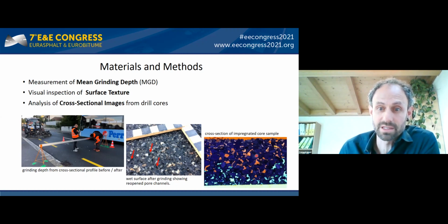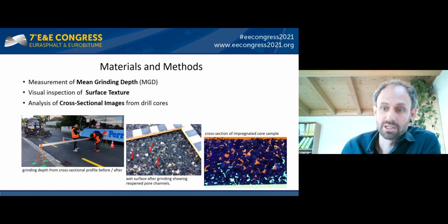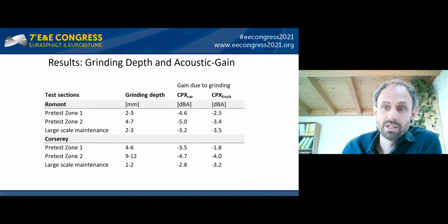Further analysis we used was cross-sectional images from impregnated core samples. With this special method, the top layer from the core was impregnated with 2 colors, first one from top and the second one from bottom. The penetration depth of the resin from top, in this case the red color, provides information on accessibility to the open pores. Now let's have a look at the results from the 2 roads.